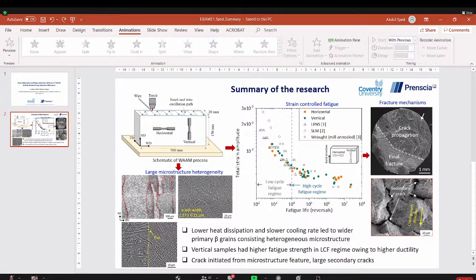Of course, going to the material aspect, it can be a little bit challenging to check what exactly is happening in the grain dimensions, but mechanically explaining, when the vertical samples are showing higher ductility, that means that during the loading we may have potentially higher plastic deformation. And as you know, for low cycle fatigue, the majority of the life is spent on fatigue crack growth instead of fatigue crack initiation. So this possible higher plasticity in the vertical samples, that we saw also from the tensile data, can create stress shielding in the material, and that stress shielding can result in the higher fatigue life that we have obtained. At least this is my interpretation.